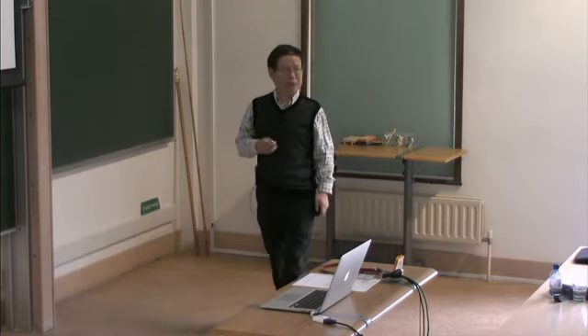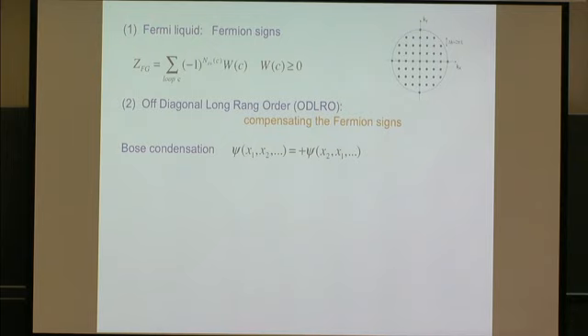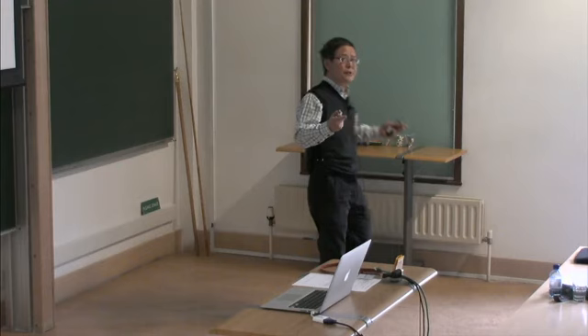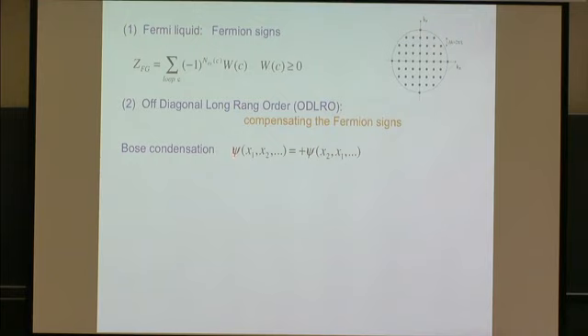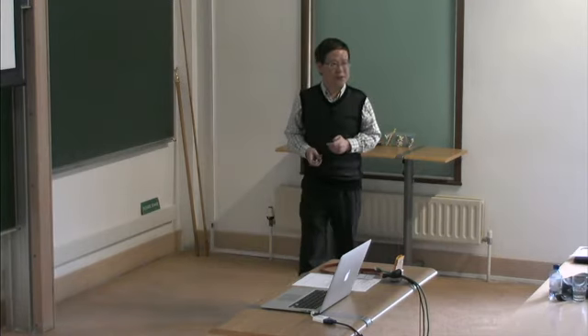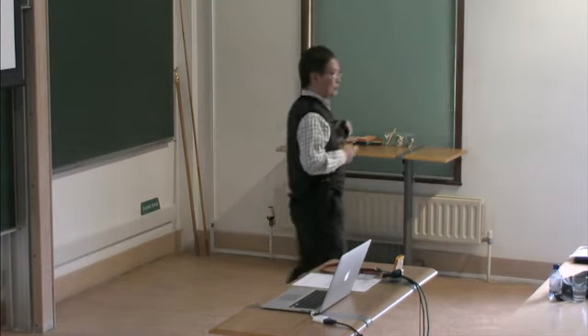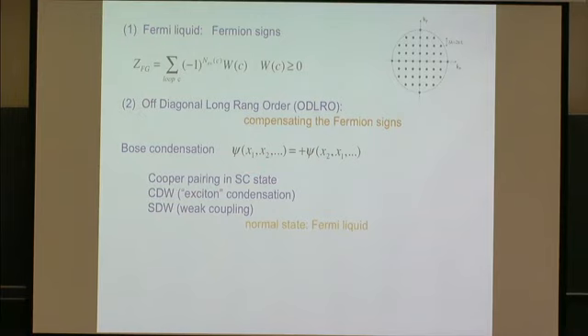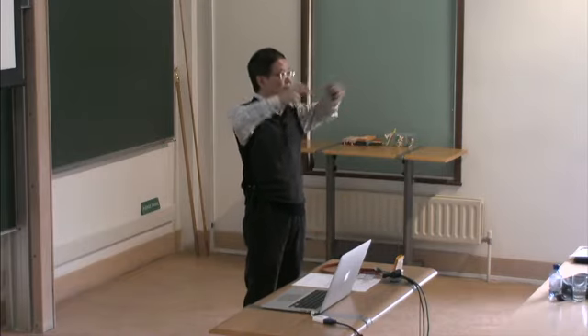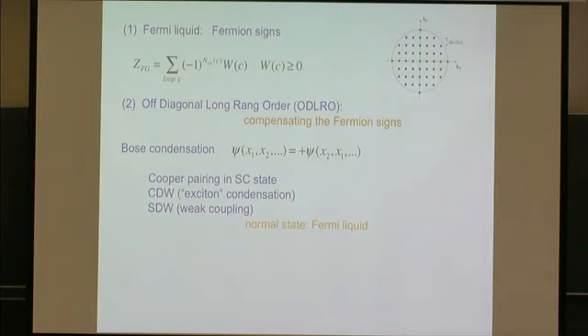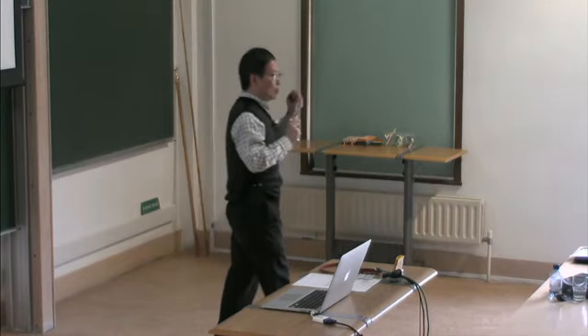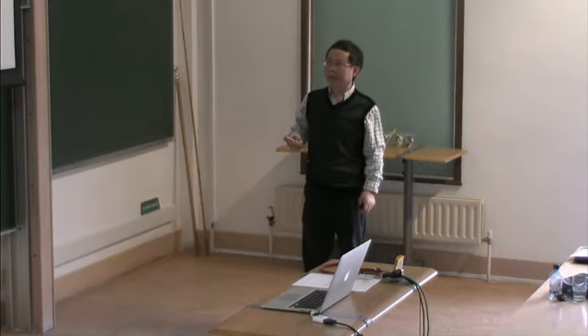But in the following, we're going to take a different route to look at this problem. Actually, in conventional systems in nature, there are other ways to overcome the fermion sign frustration. It's by forming so-called off-diagonal long-range order or symmetry breaking. For the simplest symmetry breaking system, you can imagine a boson with a symmetrical wave function, which will form a Bose condensation. But for a fermion system, there's another way to manage to make it bosonized. In the weak coupling case, the Cooper pairing forms a bosonic object when the length scale is larger than the Cooper pair size. A thin layer of electrons near the Fermi surface will form Cooper pairs. CDW, SDW, all kinds of particle-hole pairs form a boson field, such that you gain kinetic energy.